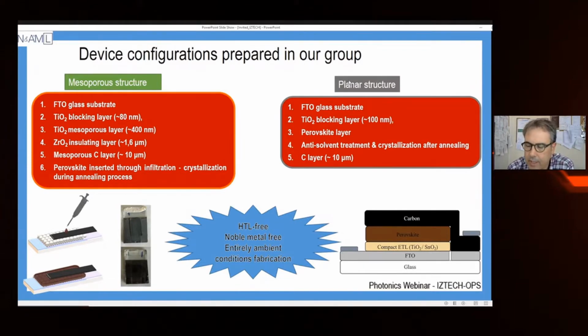The other structure here, which is, I would say, more attractive for a company, is as follows. We have the substrate of FTO, we have a blocking layer, we have the perovskite layer, then we apply a treatment with an anti-solvent, as it is called. It means that we put a specific solvent in order to increase the crystallinity of the material. And finally, we anneal the perovskite at a relatively high temperature, around 80 or 100 degrees Celsius, in order to crystallize it. And finally, we put the carbon layer.